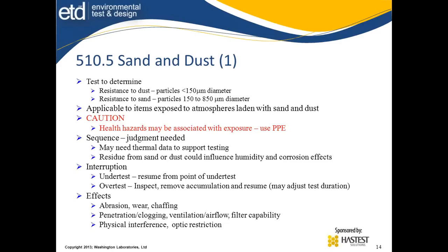The interruption: if you have an under test, you resume from the point where the under test started. If you do an over test, you've got to inspect it, remove the accumulation that's in excess, and resume. You may have to adjust the test duration. If you're very close to finishing, you may not want to run it through the whole time again.